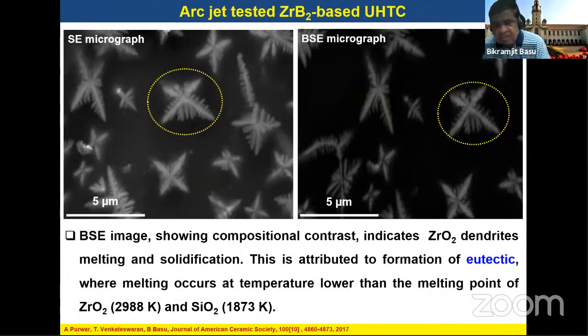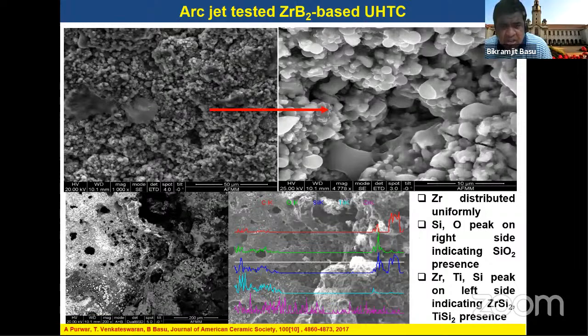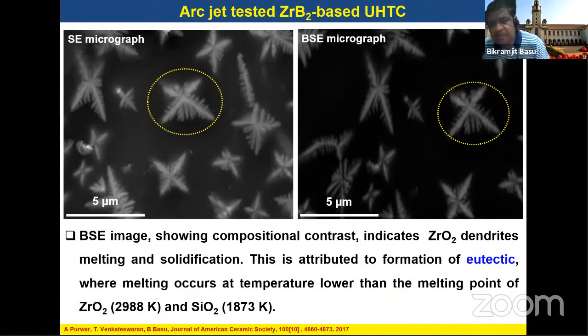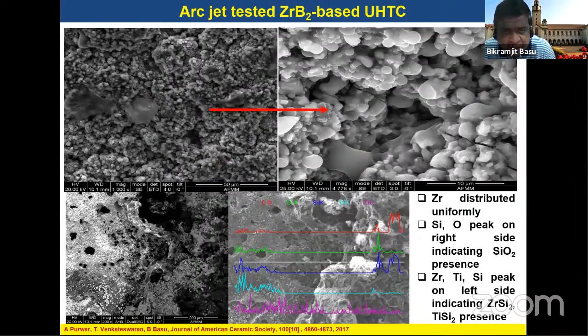What is interesting to see is that when we looked at the microstructure of these materials, we found a very dendritic type of microstructure, which people typically observe after solidification of metals. You can see the primary dendrite spacing as well as a very nice development of secondary dendrites and so on in these arc jet tested zirconium boride materials, which essentially tells us that locally this material is melted and subsequently solidified.